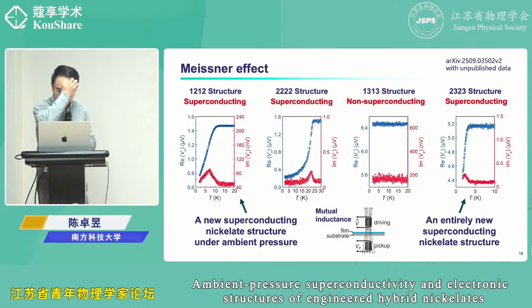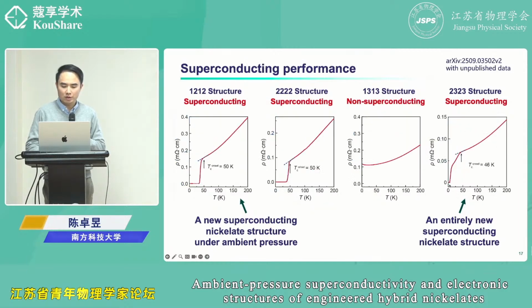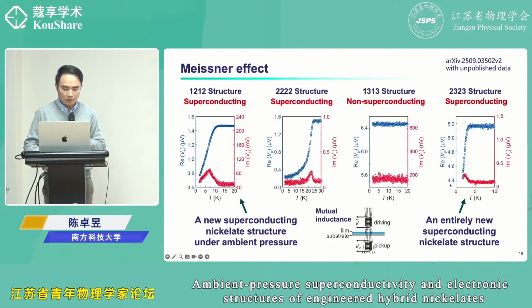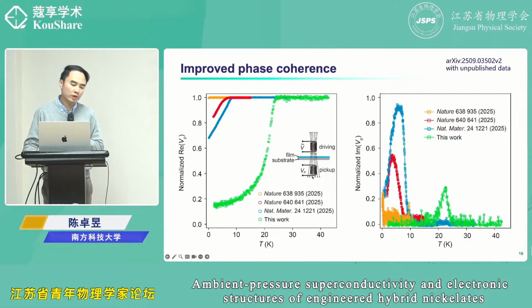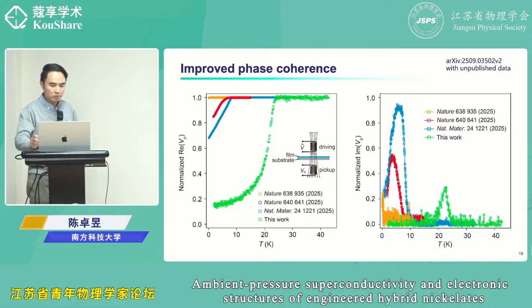Yep. So mutual inductance, Meissner effect, can also show the 3 superconducting, and 1313. This one is not superconducting. So yeah, if you look at this 2323, it shows some diamagnetism, but at a quite low temperature. It's actually matching that the zero resistance is at a pretty low temperature. But for this 2222, it's quite a big improvement compared to previous reports.